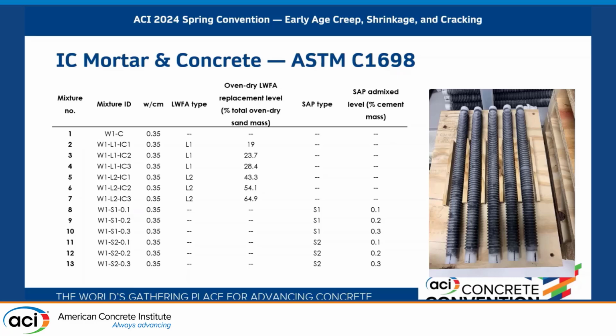Volumetric changes at early age. This is the 1698 test that Jason mentioned, the corrugated tube that was used for evaluating different sources. In this case, I'm just showing a portion of the combinations of materials that were used. In this case, there are 2 lightweight aggregate sources and 2 superabsorbent polymers at different ratios or different dosages.